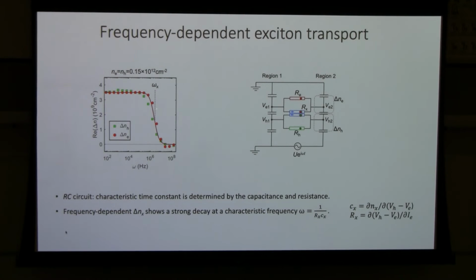So we can think about this decreased signal at higher frequency using an effective circuit model. In the case where we have only excitons, we can simplify the model to be an effective resistance for exciton flow, and then at the two gates we have an effective capacitance for this exciton, and the RC constant will determine this transition frequency. So what are the capacitance and the resistance for an exciton?